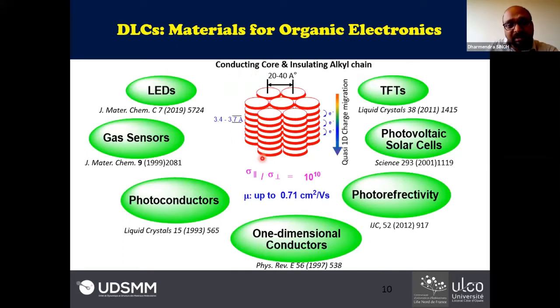You see here, these disc-shaped molecules are arranged in columns, and later on the columns are arranged in a hexagonal way. These molecules self-assemble in columns via pi-pi interaction, and the geometrical shape can be hexagonal, rectangular, and so on. The intercolumnar distance between two columns is around 20 to 40 angstrom, and the intracolumnar pi-pi distance is around 3.5 angstrom. These molecules show unidirectional charge transport via a hopping process, where an electron or hole hops from one disk to another along the column.